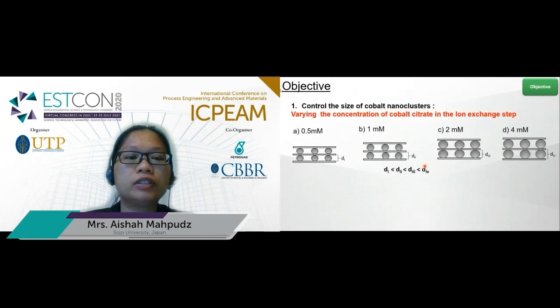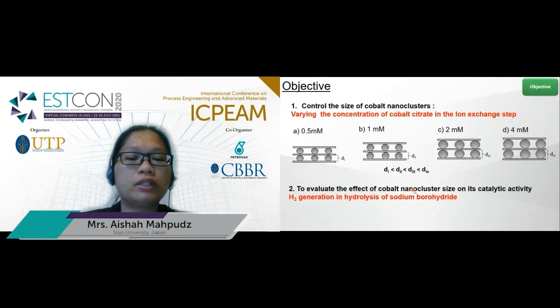So the objective of this research is firstly to control the size of cobalt nanocluster, and this is done by varying the concentration of cobalt citrate in the ion exchange step. And secondly, to evaluate the effect of cobalt nanocluster size on its catalytic activity, and this is evaluated from the hydrogen generation from sodium borohydride hydrolysis.